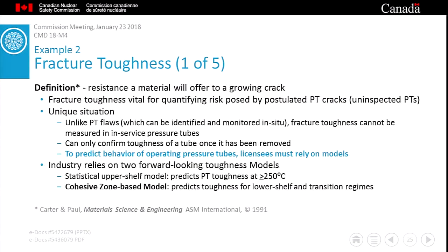At this point, it's important to re-emphasize an earlier comment. While pressure tubes are designed to be leak-free for life, CANDU designers allowed for the remote possibility of a crack. They deliberately built in features that would resist the growth of a through-wall crack, irrespective of how it got there. Fracture toughness is a measure of that resistance. Practically speaking, if a crack develops in a high-toughness tube, it will take a while to grow to an unsafe length. And that is the time during which operators can identify the leaking tube and take action to safely cool and shut down the reactor.